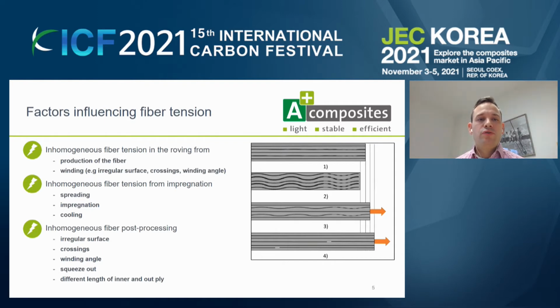This leads usually to irregularities of the bobbin surface, and this leads to a different tension in the roving. As more fibers are on the yarn, the stronger are these effects, and also their crossings and the angles are very, very important. We investigate now many different carbon fibers and glass fibers, and this is really a very critical point, and there can be a lot of improvements done.